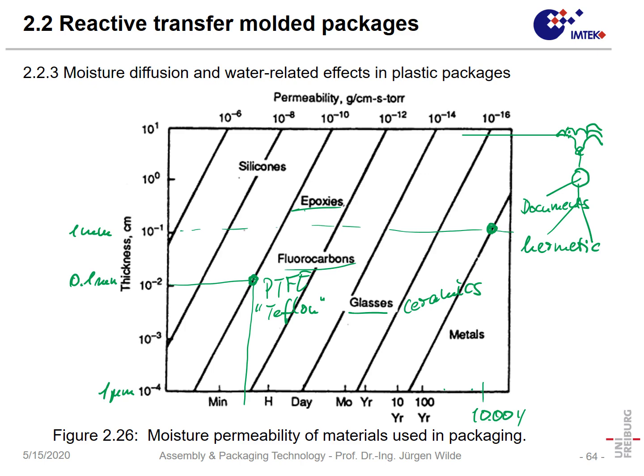Silicones, so silicone rubbers are very frequently used for sealing something. Yeah, if you have something like a gap in your bathroom, you use such silicones. Also, silicones are often used for electronics to embed these. So that's a little annoying, because why do we use silicones when silicones are so bad? So you could say silicones, it's less than a minute until water penetrates 0.1 millimeter, 100 micrometer. They are nothing against moisture, they are like a sieve. So why do we use these?